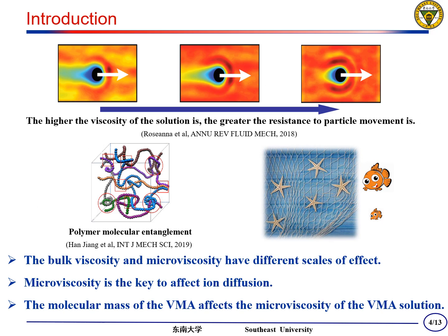Stokes-Einstein equation indicates that the higher the viscosity of the solution is, the greater the resistance to particle movement is. But what happens when the scale is narrowed to the ionic level? The association and entanglement between adjacent polymer chains of VMA lead to the formation of three-dimensional network and the hydrogen bonds in solution, which gives the solution a high viscosity.